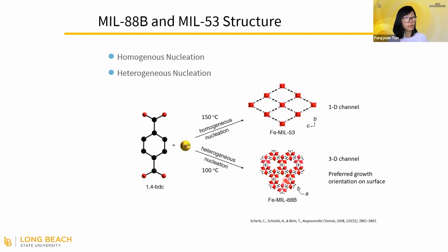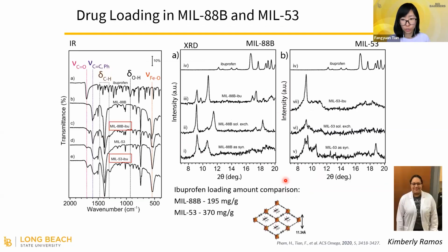But at the very beginning, we had no idea which one would be better, so we tried both. My students, Kimberly and Hal, did all of those experiments, and we found that MIL-88B can load around 28% of ibuprofen, while MIL-53 has a much higher drug loading amount, around 37%.